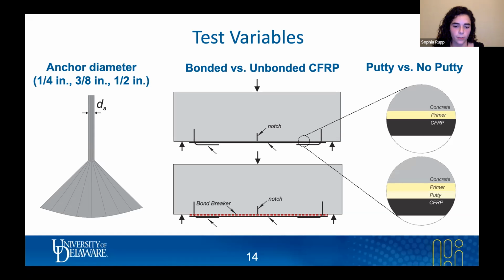In my case, I'm using a very thin layer of Teflon tape, and this is so that we can study the anchor capacity alone. And then the last variable that we're looking at is whether or not we include that layer of putty over top of that initial epoxy coat. And the reason for that is to see just how effective the use of that putty is in increasing the bond durability or increasing the bond between CFRP and concrete.